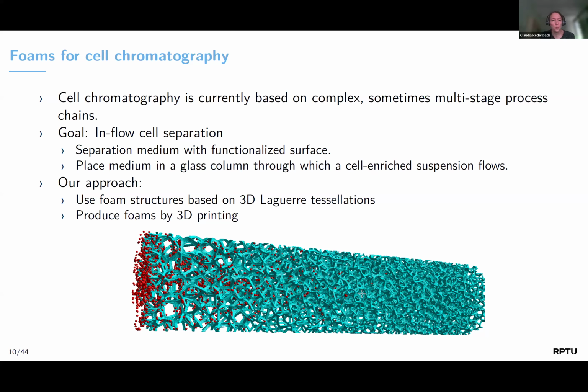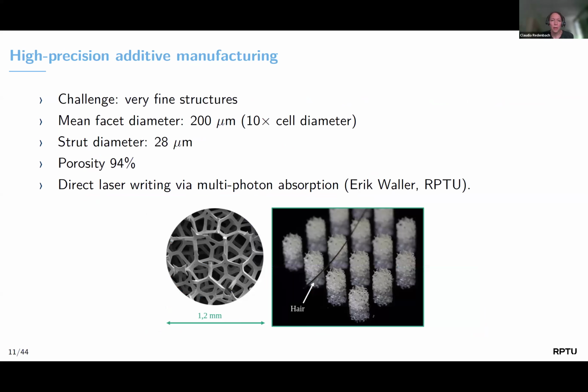What we did here was that we modeled the cell systems by Laguerre tessellations, and then we produced these foams or the filter media by 3D printing. So this is shown here. The challenge was that these are very delicate structures. So cell diameters are around 20 microns. So we decided on facet diameters in the range of 200 microns. And we needed very specialized 3D printing equipment done by colleagues here at RPTU. Here you see a picture of such printed foam samples, and you see a hair for comparison of how small these structures actually are.